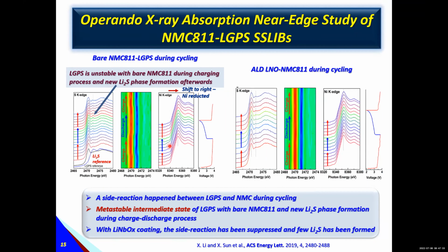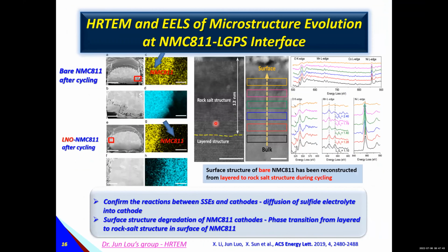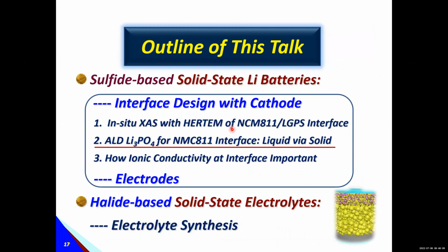This is without ALD coating, some reactions. With ALD coating, you can see this kind of reactions. So we also try to understand what happened near the surface. We're using high-resolution TEM. We see that here is 12 nanometers at the surface. We found structure change, phase transition from layered structure to rock salt structure at about 10 nanometer depth. So in this case, we see that we do have a lot of reactions we need to address.